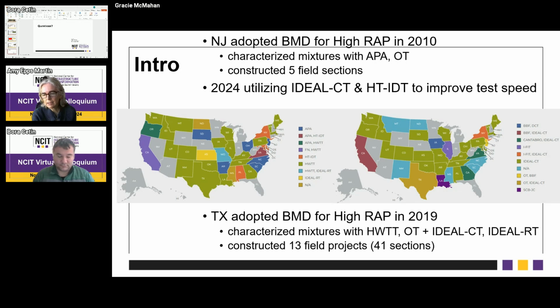Texas, on the other hand, adopted BMD for high RAP mixtures in 2019, so maybe less experience, about 5 years of experience. And we are involved in a large implementation project where we're running repeated load tests, the Hamburg wheel tracking test, and the overlay test, and the more practical IDEAL cracking and rutting tests. Right now, we have about 41 sections across the state of Texas that are in 13 different field projects, which means locations in terms of climate and materials. And the maps just show you that this balanced mix design and what tests are being used is just kind of exploding all across the country.